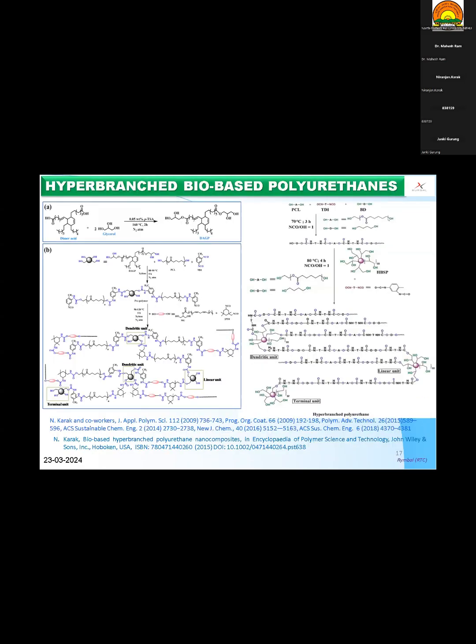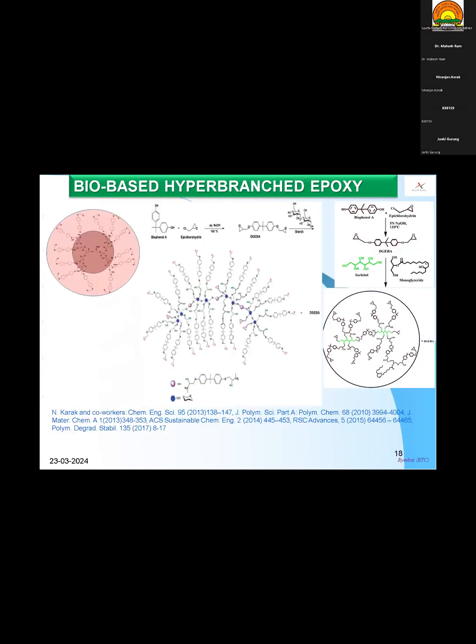However, our main research focus was on hyperbranched bio-based polyurethane, because polyurethane is the most versatile polymer because of its inherent soft and hard segments in the same structure, and this heterogeneity is inherent, and hence you can play around its structure by controlling the hard and soft segment structure and position, and hence you can play around the property and its case. Thus, most of the polymers or rather products are obtained from these, and that I shall discuss in a later part of my lecture. Another industrially important polymer is the epoxy.